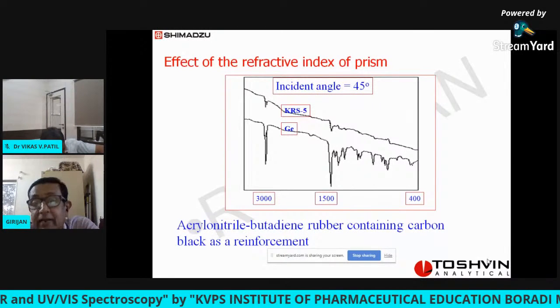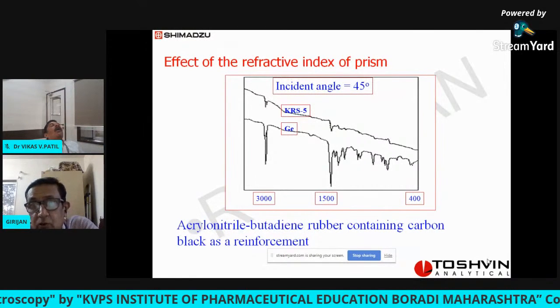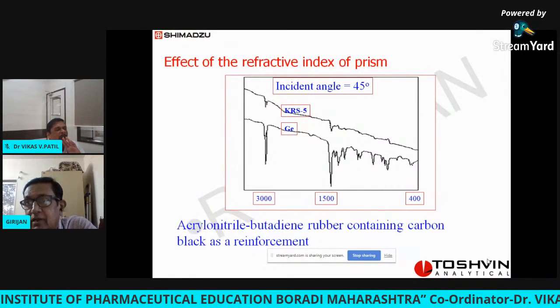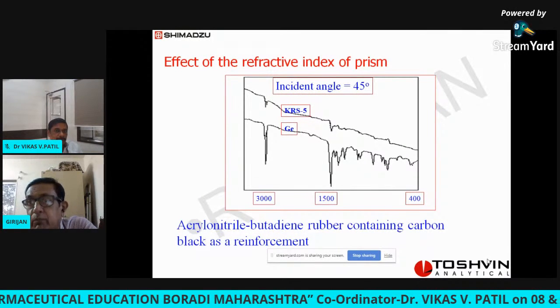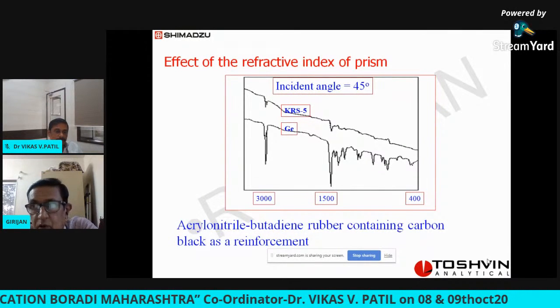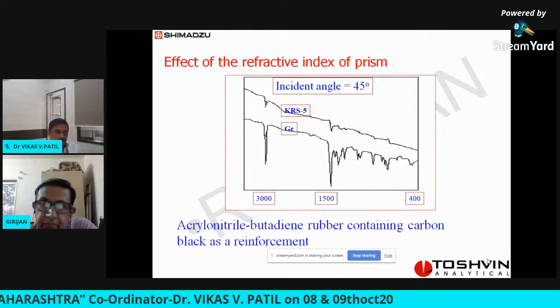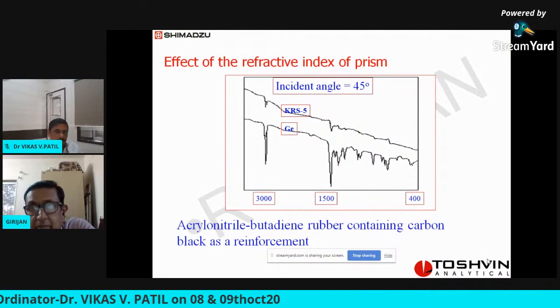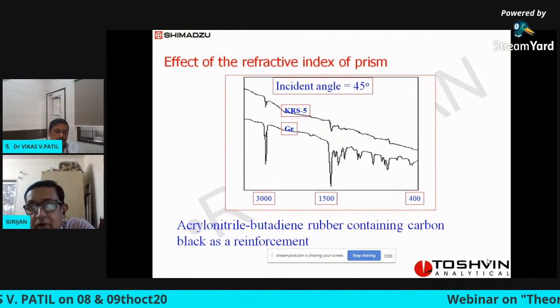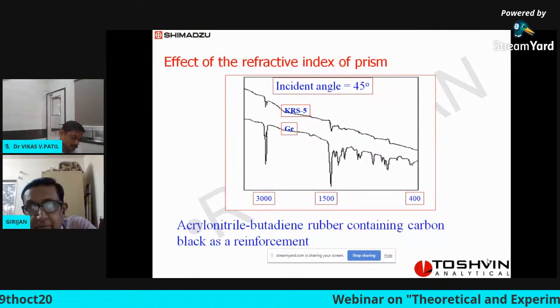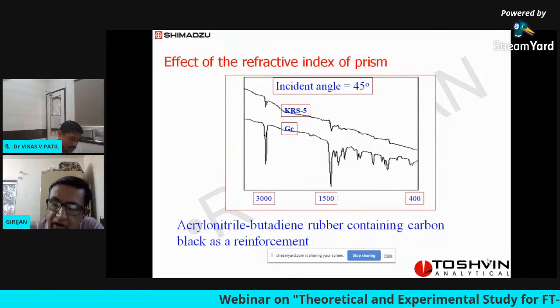But if you use a germanium prism, germanium is the only crystal which has a refractive index of approximately 4.2 or something, which is more than carbon black. So for any sample containing carbon black or black material, you have to always use only a germanium prism. Then only you'll get a quality spectrum.